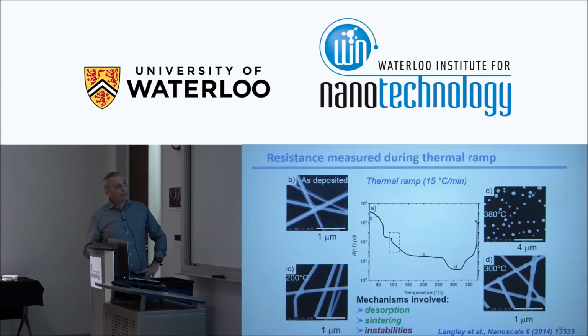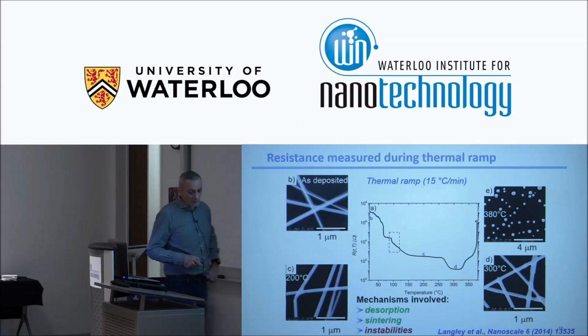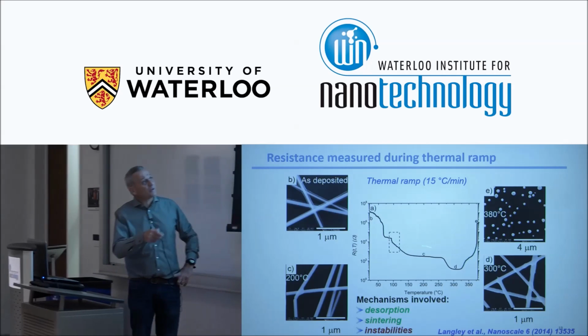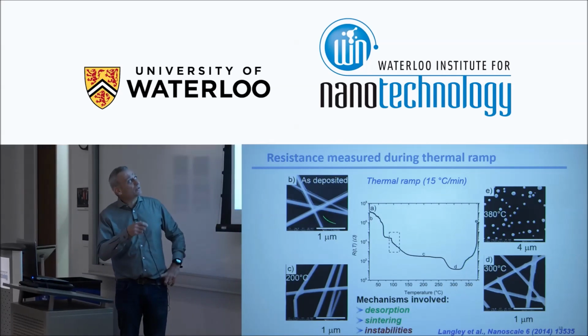What we did, we observed as well, we measured the resistance versus temperature during a thermal ramp, where we increased the temperature at 15 degrees per minute. We started with a very high resistance, and then this resistance was decreasing, reaching a minimum, and then kind of a divergence of resistance. So we kind of intuitively guessed that it would be a curve like this, because at the beginning you could have some desorption.